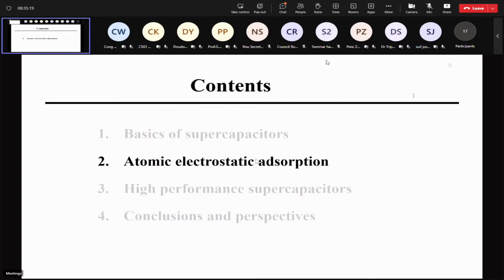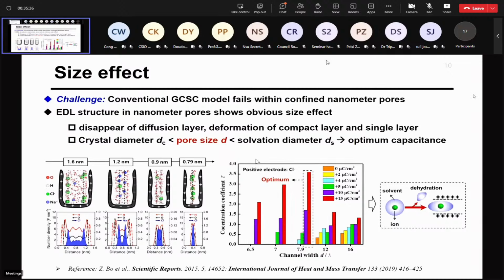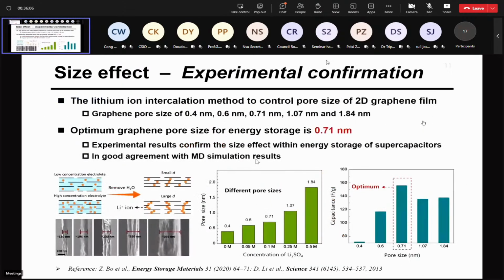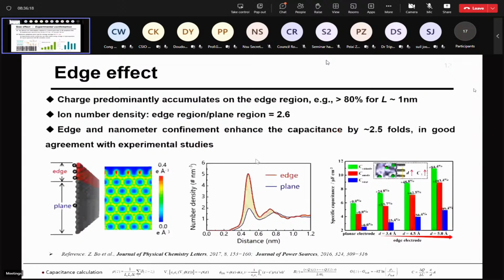So in our group, we conducted a lot of work on multi-scale numerical simulation and microscopic measurements to review the atomic electrostatic adsorption mechanism. The conventional model fails to describe the effect of confined nanometer pores on the electrostatic adsorption. So we use MD simulation work to review the EDL structure in nanometer pores, and it shows an obvious size effect. As you can see from the figure, there are a lot of unique ion structures in the nanopores. We also conducted experimental work to control the pore size of the two-dimensional graphene film, and it confirmed the size effect very well.